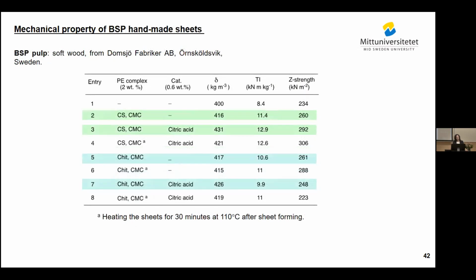Also, I did the same experiment with the bleached sulfite pulp, and we see that in the presence of citric acid, I could increase the Z-strength and tensile strength of this pulp. But with the same result as CTMP when I had chitosan, we don't see a clear effect of the catalyst here.